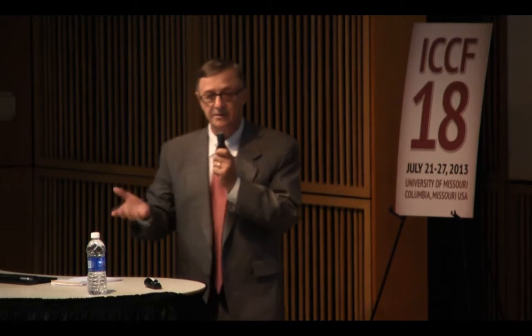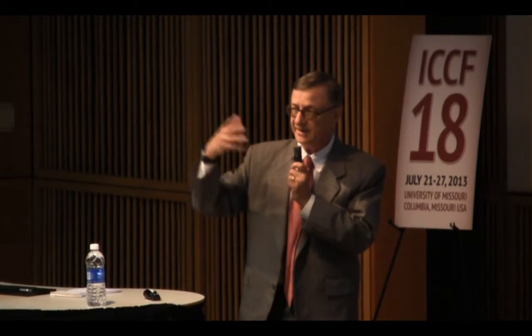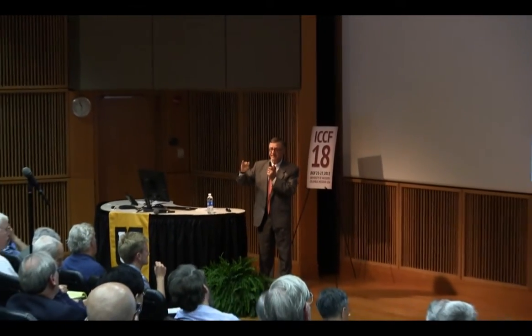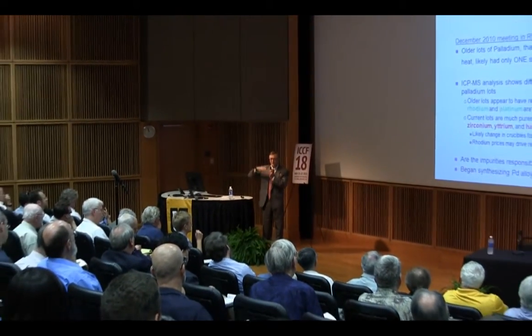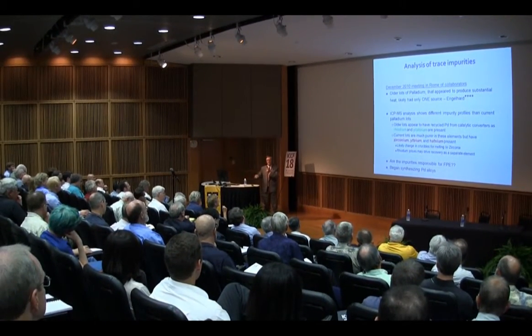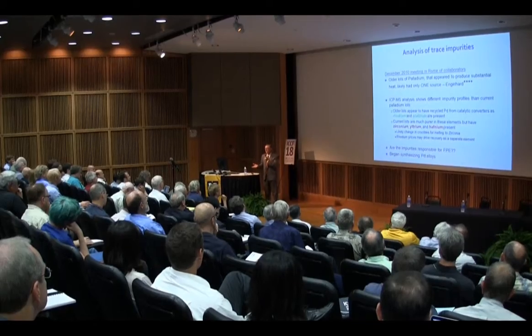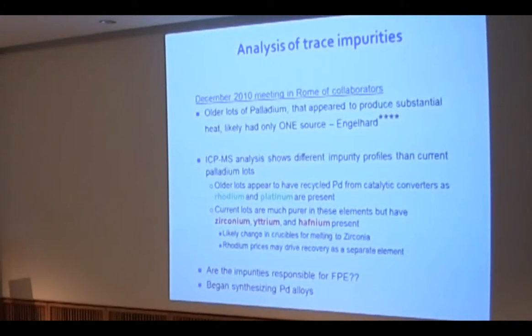And what we also found out later on, and this slide was given by David Kidwell, and I'm just going to reiterate what's on this slide, is that there's zirconium in the newer material, sometimes up to 10, 20, 30 parts per million. Now, a speculation is that in this highly defective material, when you ramp up the anneal, that zirconium will transient enhance transport and go to the grain boundaries in some kind of stochastic way, and will just pin the grain boundaries and give you kind of random morphology when you finish and you etch the material.